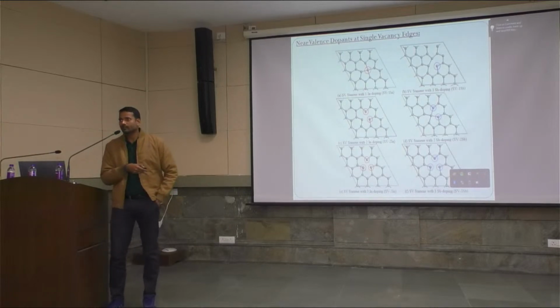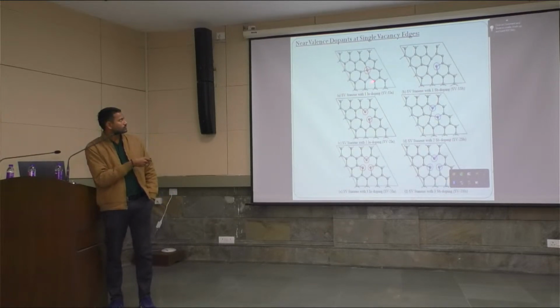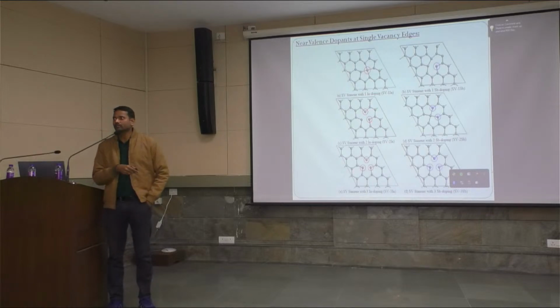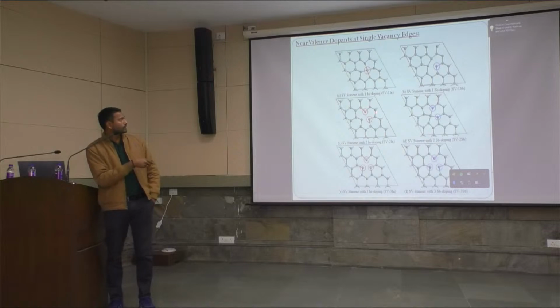To further study the different mechanisms, we have introduced these near-valence dopants, indium and antimony, at the SV edges, the single vacancy edges. Initially, one indium is positioned at the single vacancy edge. Thereafter, two indium atom dopants are positioned at the SV edges. Thereafter, three indium atoms are positioned at the SV edges. And similarly, the antimony dopants are also positioned at the SV edges. We have seen that as we position more dopants at the SV edges, the stability increases. This can be attributed to the elimination of dangling bonds by positioning these dopant atoms.